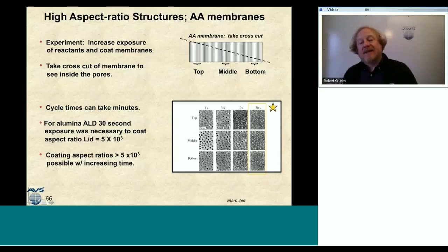At 3 and at 10 seconds, you can still see that the middle has a lower, thinner deposition than the top does. But then when we do exposures of 30 seconds or longer, both pulses and purges, you can see that the holes are about the same size. The open hole at the top is equivalent to the size of the open hole at the middle, and is equivalent to the size of the hole at the bottom.